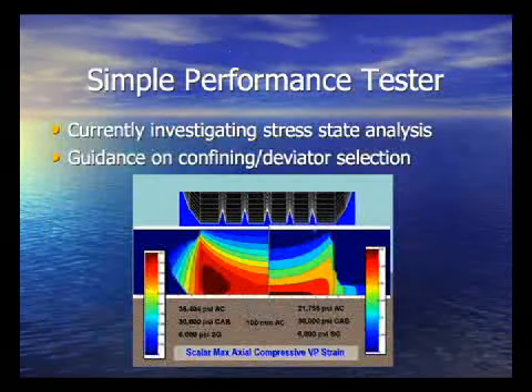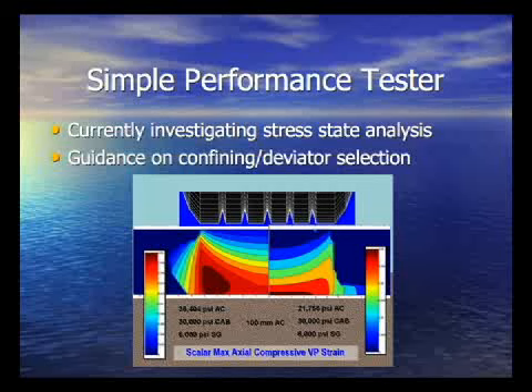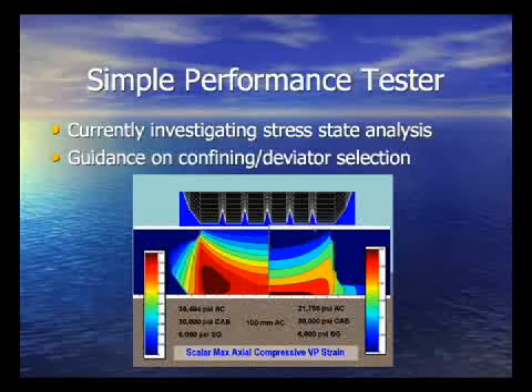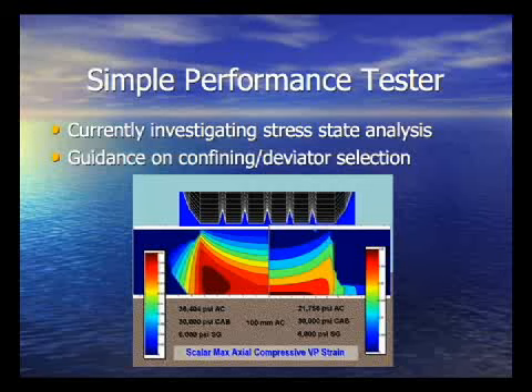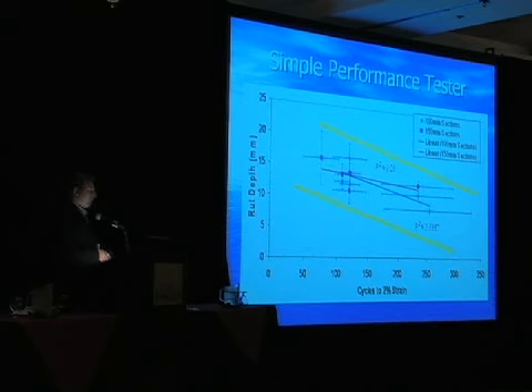Now, these were unconfined tests, and we're currently performing some tests under confinement, and I'll mention very briefly, this is an analysis where we're looking at the multi-axial stresses under a wheel, which determine which location is rutting under the ALF being mostly disturbed. What's the hot spot? What's the most disturbance? And then tailoring a confined repeated load test to those conditions. That's ongoing right now, but if you look at the results from unconfined repeated load testing, it's very good.